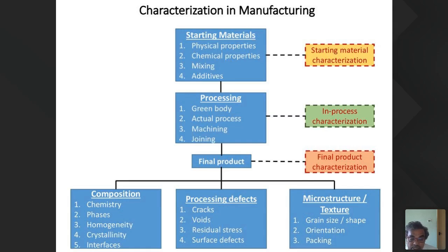You have to see whether there is any change in the chemistry during service. Let us say you are going to do some welding. As I mentioned earlier, you are going to weld a stainless steel material. So you have to select the right material which does not deplete the chromium. When you are welding the stainless steel, there will be some amount of chromium depletion. If the chromium is getting depleted, it starts corroding. Then corrosion will create a problem during service. The component will fail.